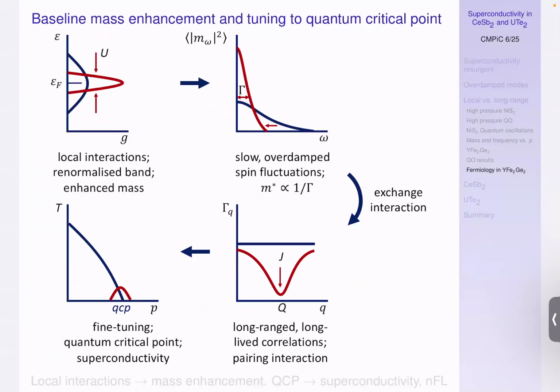So this is what I'm trying to get across. My picture here is that we start out with a weakly interacting system which has broad bands, like the blue one. We then have a local mechanism, like Hubbard repulsion, or maybe Hund's rule coupling, could be in iron-based superconductors that you would say is a Hund's metal. Basically, it's the tendency of the several electrons which sit on each iron site to align their spins. They're basically forced to align their spins locally.